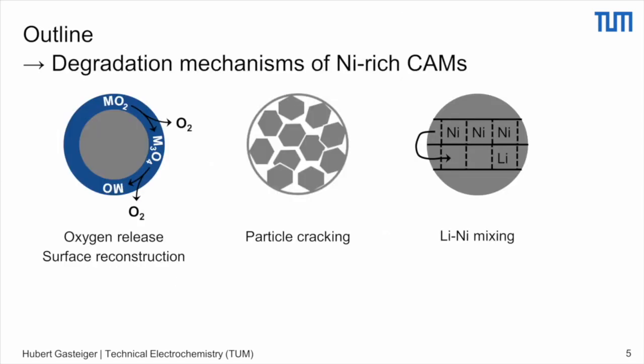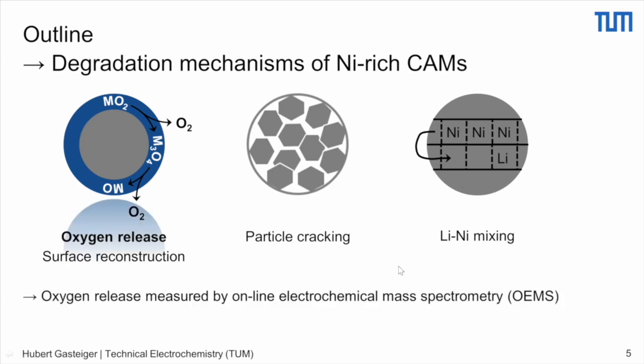So the talk is split in three sections. One section relates to oxygen release and surface reconstruction. The other one has to do with particle cracking, and the third one with potential lithium nickel mixing. So the oxygen release, we typically measure with online electrochemical mass spectroscopy, OEMS. And the studies we had conducted in the past in this regard